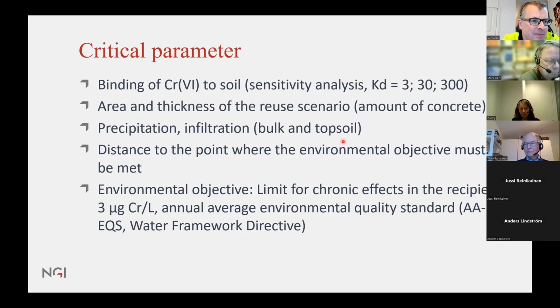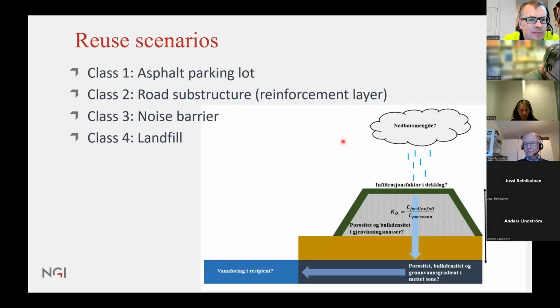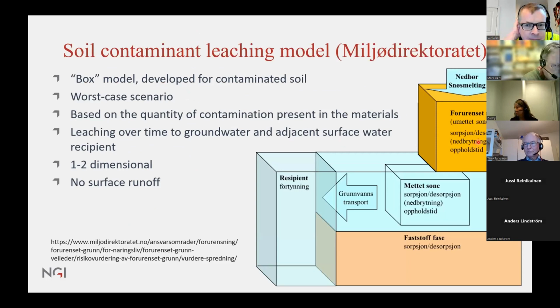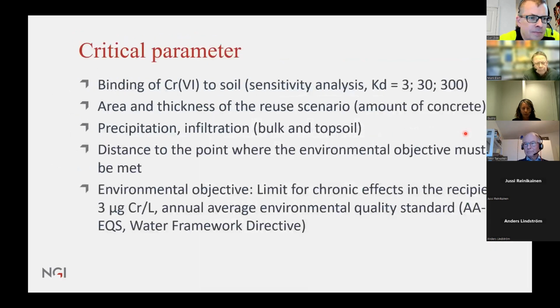And the critical parameters in the model: here, it's not a kappa value that is used, it's a KD value. The leaching from concrete is not leaching from soil, so it's a little bit different, of course. But I would say it's more conservative because you're using KD values, which are quite low in this case. But this is, of course, something which could be improved through a kappa way of describing the leaching. So the KD values we used in our modeling were 3 and 300 liters per kilogram, where 30 was the one which is default in the model from the authorities when you use it for contaminated soil.